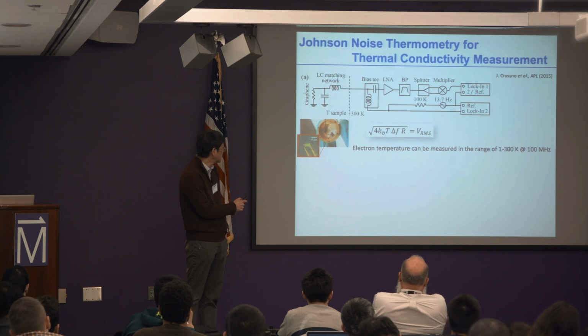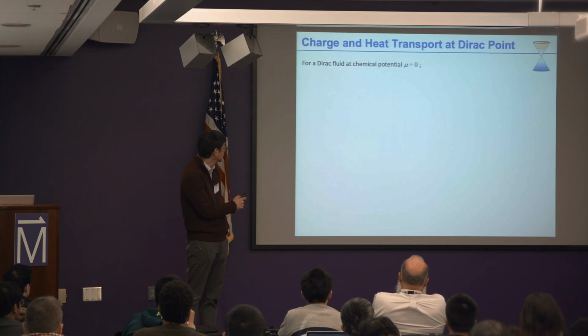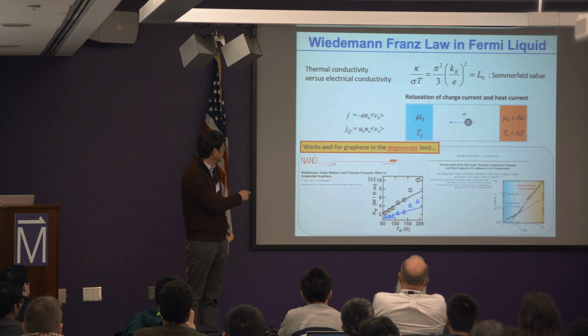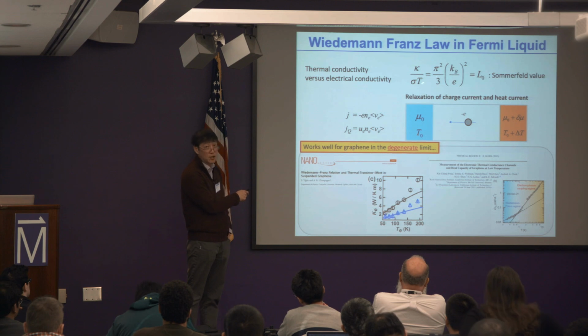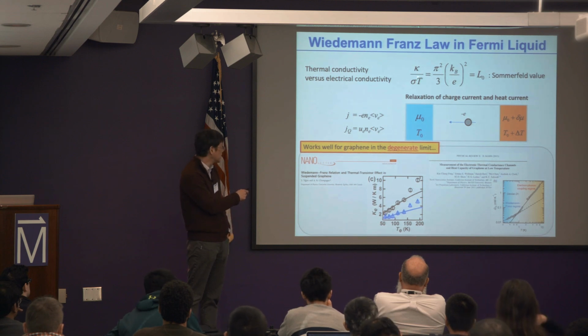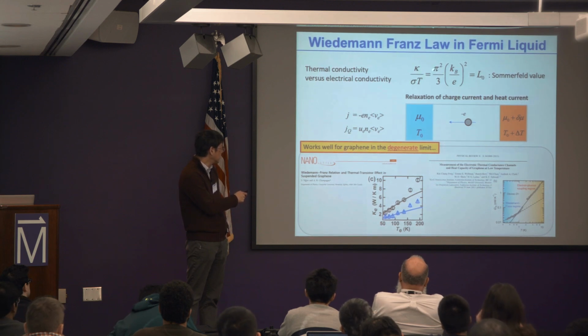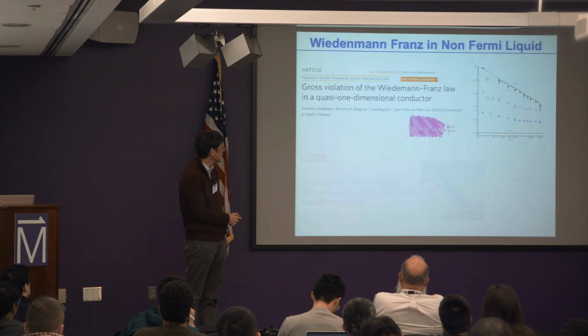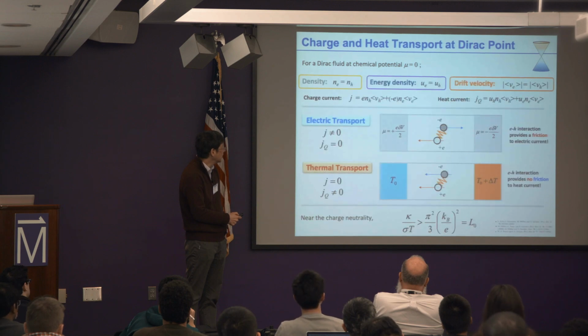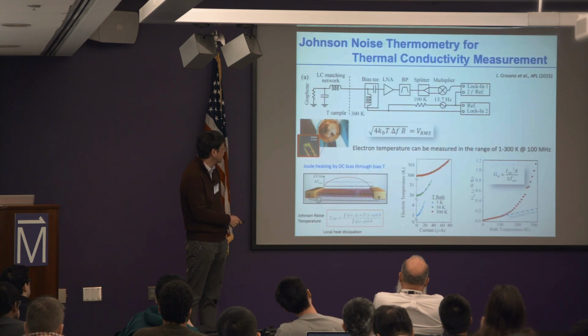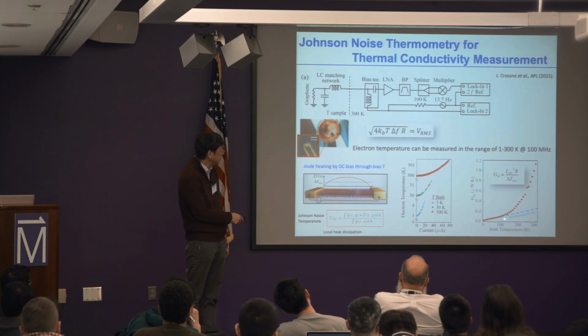If we just take the slope, this is basically exactly what the Wiedemann-Franz law expects. Note that if the Wiedemann-Franz law works, the thermal conductance is proportional to sigma T, and sigma does not change much with temperature, and T is just temperature. So we expect a linear change of the conductance with T, where the slope is basically the Sommerfeld value, and that's exactly what we are seeing in this type of experimental curve, right? And it becomes superlinear at 100 Kelvin or 150 Kelvin-ish.